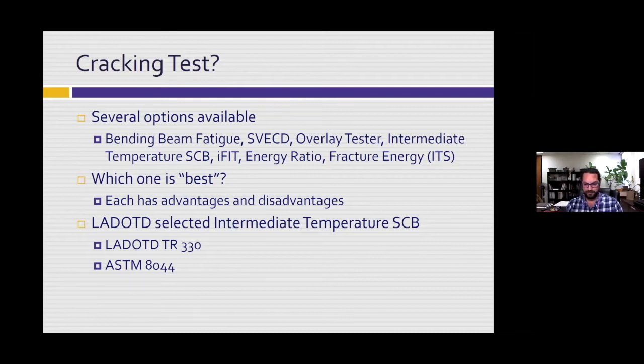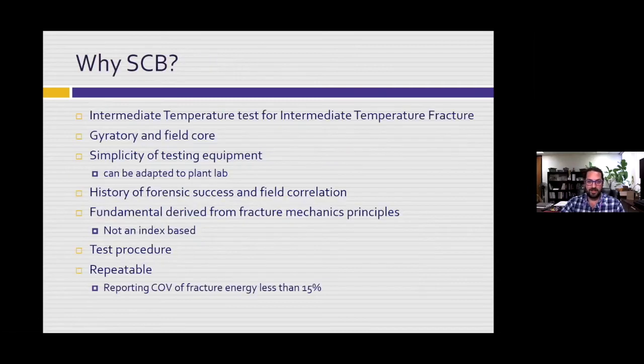If you have higher density, you expect to see reduced cracking resistance. Those types of things have to logically make sense for you and your agency in terms of which cracking tests to evaluate. So Louisiana DOT, with the comfort level and the correlation we saw to our field performance, we selected the ASTM 8044, which is the intermediate temperature semicircular bend test.